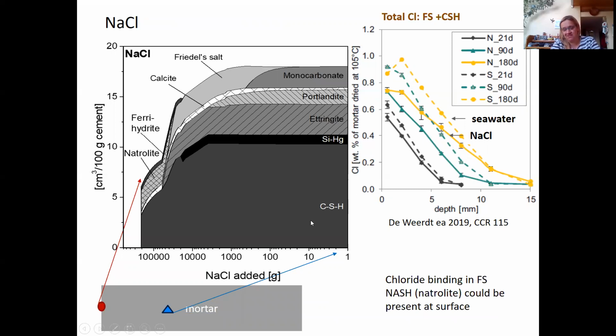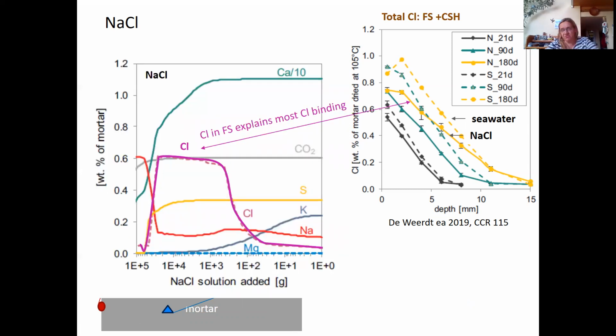Basically, here on the right-hand side is the hydrated cement, which sees no or very little sodium chloride. And to the left side, we start to see more and more sodium chloride solution. Similar to the carbonation, we predict leaching near to the surface. We predict destabilization of portlandite and of CSH. And in addition, we predict the destabilization of monocarbonate to Friedel's salt. And Friedel's salt is also the solid, or the hydrate, which binds chloride.